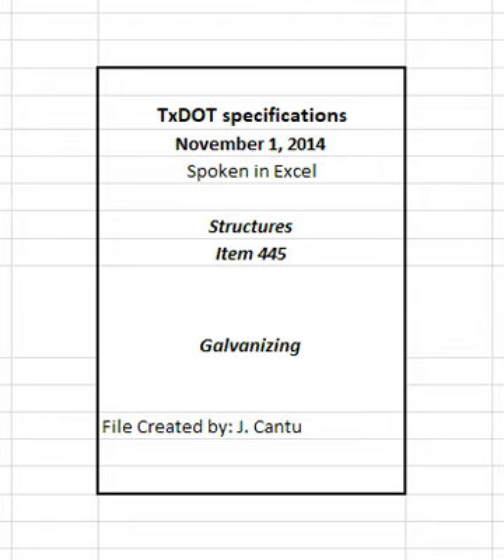3.5.2.3 Organic zinc-rich paints. Remove oil, grease, corrosion products, and welding slag or flux from surfaces to be repaired, and ensure the surfaces are clean and dry. Clean surface to near white metal by wire brushing, light grinding, or mild blasting extending into the surrounding undamaged coating to provide a smooth repair. Spray or brush apply the paint to the prepared area in accordance with the paint manufacturer's instructions to attain the required dry film thickness. Provide multiple passes when using spray application.